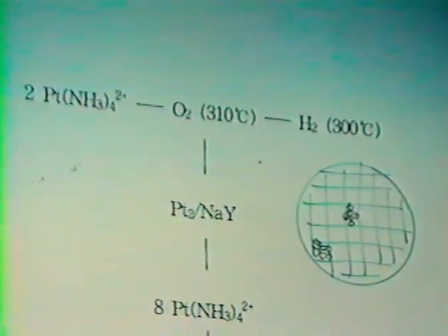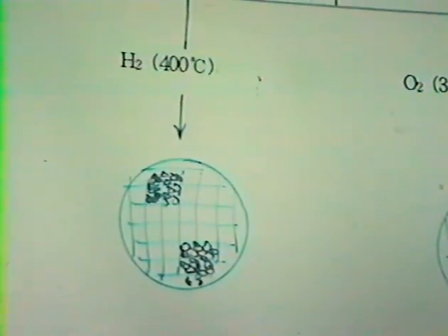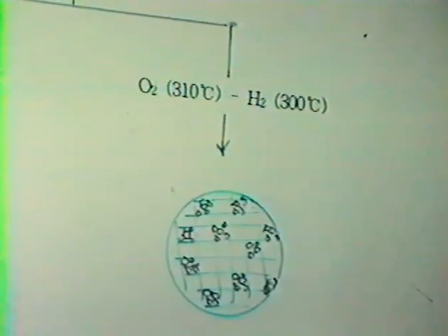This is the study. We did preparation of platinum here, and then we added additional platinum here. When we directly reduce, all the platinum atoms go to the first platinum cluster. But if you follow calcination reduction, you obtain separate platinum clusters in other supercages.